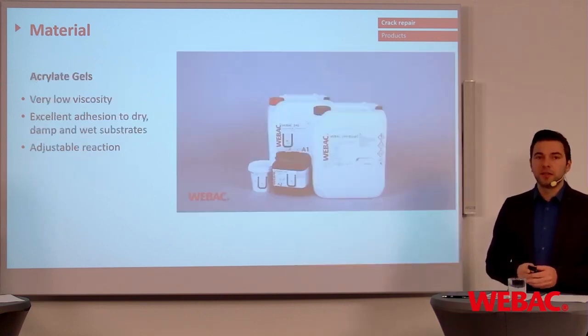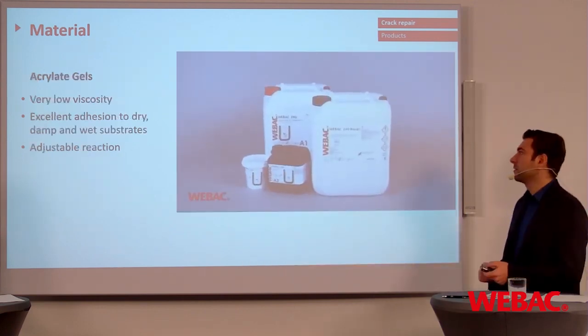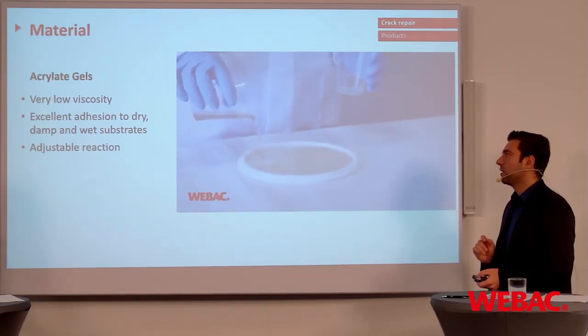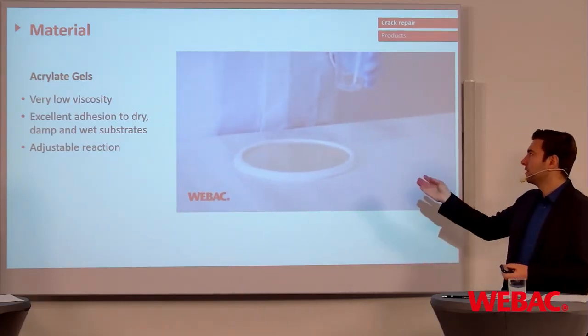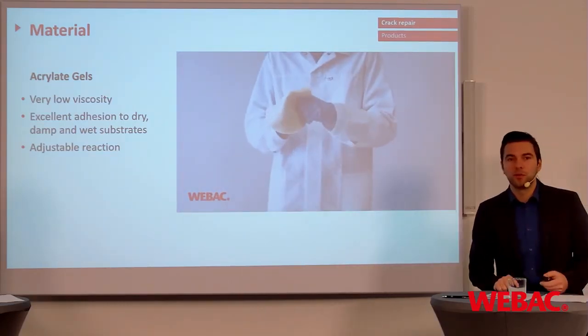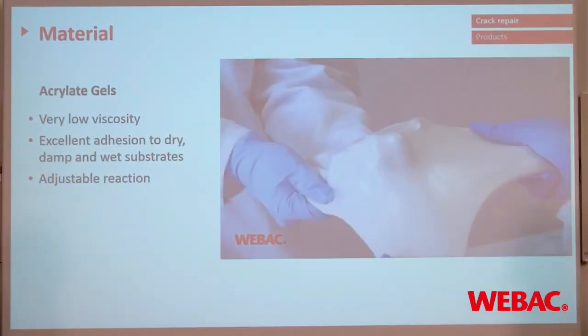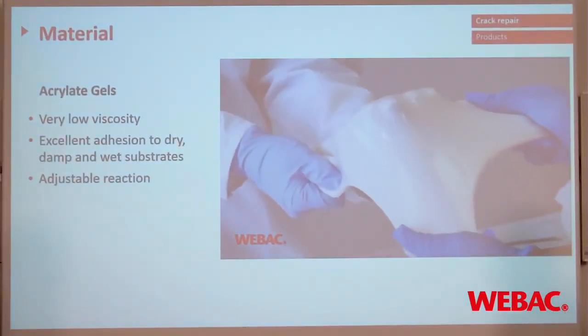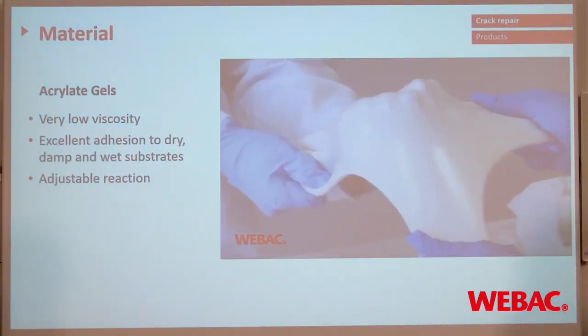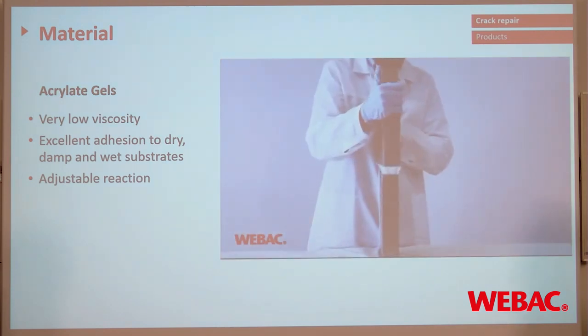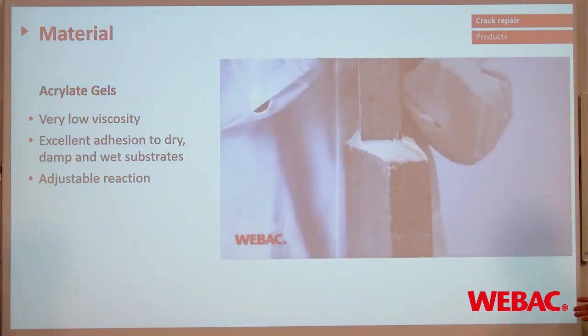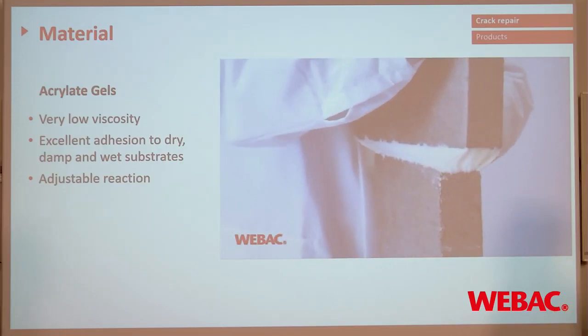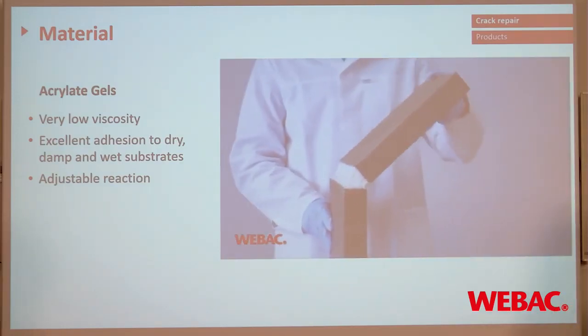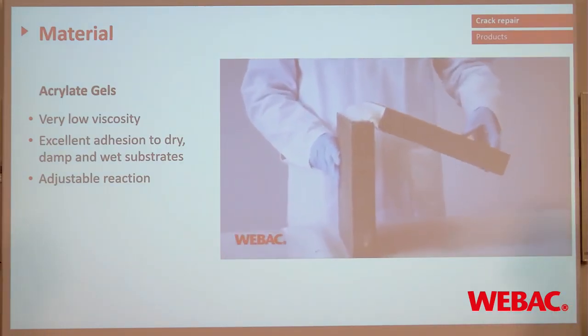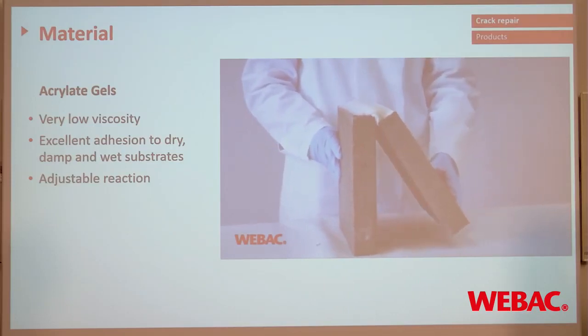And finally, the swellable fitted fillings are the acrylic gels. As you can see in the video, they have a very, very low viscosity, meaning it's more or less comparable to water. They also have a very good adhesion to dry, damp and wet substrates, and the reaction time can easily be adjusted by the amount of component B, the initiator of that product.